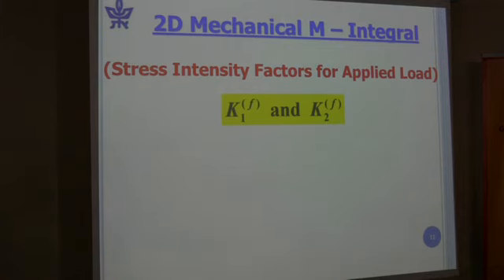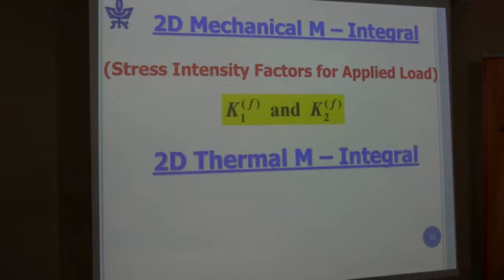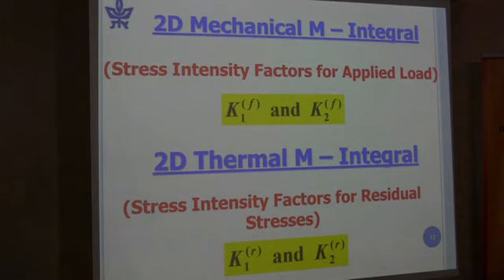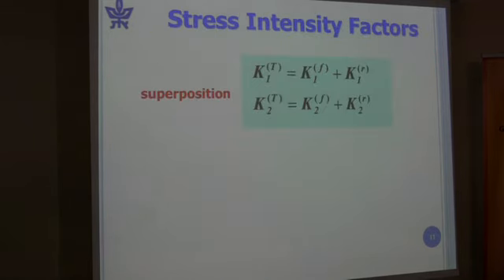These were cured at 177 degrees Celsius. So you also have residual stresses, and we obtained K1 and K2 for residual stresses, also from an M integral. So now we take our Ks, and we have linear elasticity. We don't have plasticity in this case. It's very, very small. These materials are brittle.